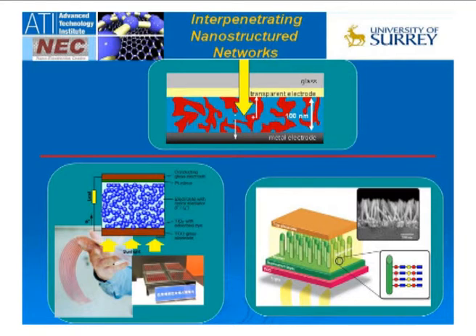Right? Suddenly, if we were to look at it from this scale point of view, your crystalline silicon would have started there and it had gone all the way down, 1,000 times larger. So we've decreased the volume hugely. But when you decrease the volume hugely and have these materials that are hugely absorbing, we have a problem, because once you create your absorbed electron hole, which is called an exciton, those excitons cannot diffuse very far. They can only diffuse to about a maximum of 10 to 15 nanometers. So there's the problem. You need to have 100 nanometer thick material, but its diffusion length is only of the order of 10 nanometers.